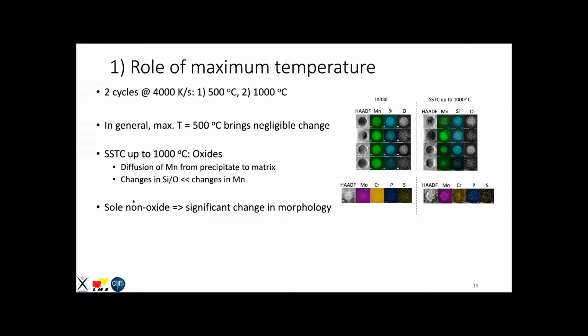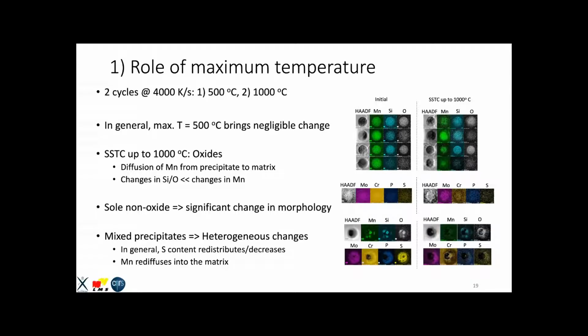There was only one pure non-oxide inside this lamella. This one changed significantly in geometry. You can see here it's quite distorted compared to this, and this has resulted in a change in the chemical composition as well, of course. In mixed precipitates, there were a bunch of different changes happening, but there was some commonality. In general, the sulfur content was redistributing and decreasing. And manganese continued to rediffuse into the matrix in all these cases. So that was the case of maximum temperature.